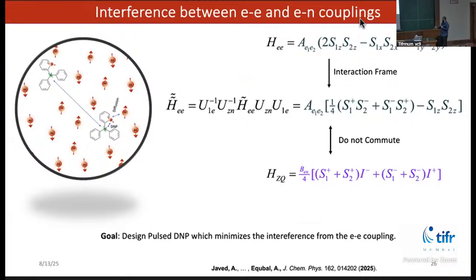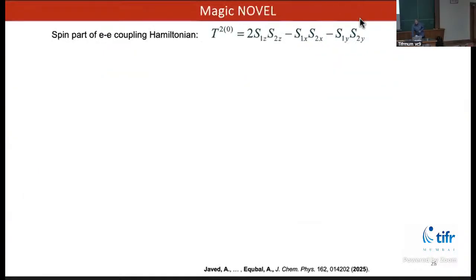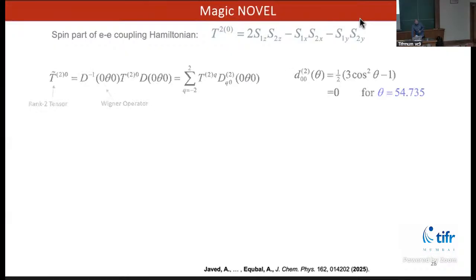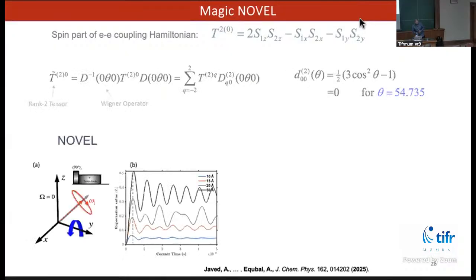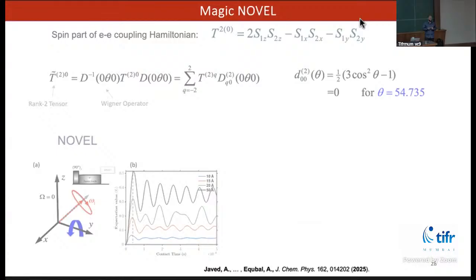So that's the basic idea, and we wanted to overcome this. We found that one way to overcome this limitation is very simple. What we have to do is something like an effective rotation at the magic angle. Those who have done solid state NMR would know that whenever solid state NMR is done, the sample is rotated at the magic angle. It's rotated at an angle of 54.7 degrees.